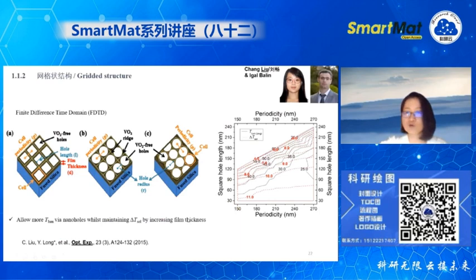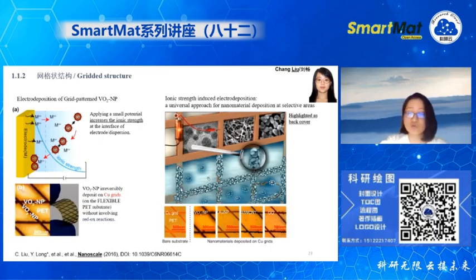Okay, so we quickly move towards some new ways. We use FDTD, collaborating with my Israel partner. So we know once we created all these graded structures, we can also enhance T_lum and delta T at the same time. My student went to Israel because she is a double degree student, which means she has two degrees from both Singapore and Israel. She used this electrodeposition way to directly deposit vanadium dioxide on the graded structures. By doing so, we can get much enhanced T_lum and delta T at the same time.